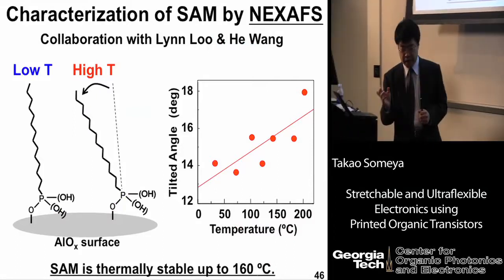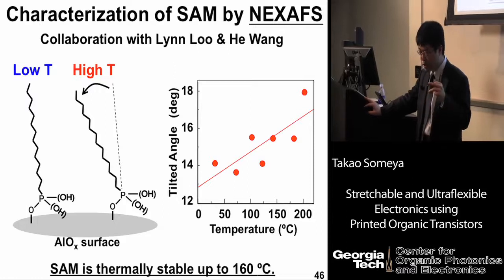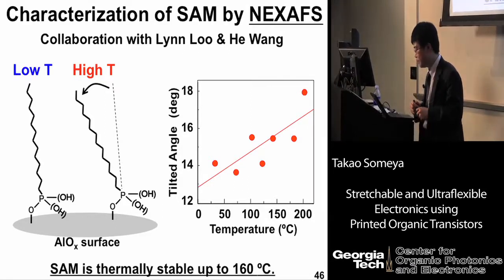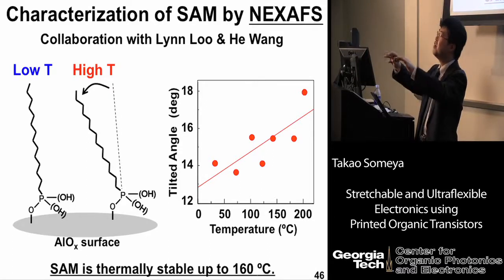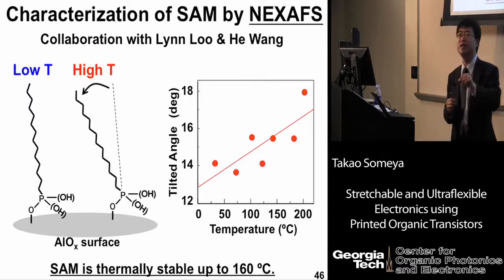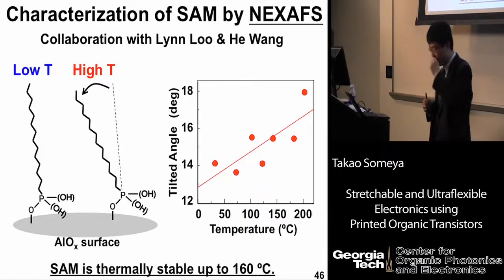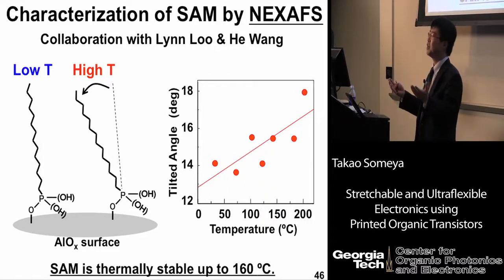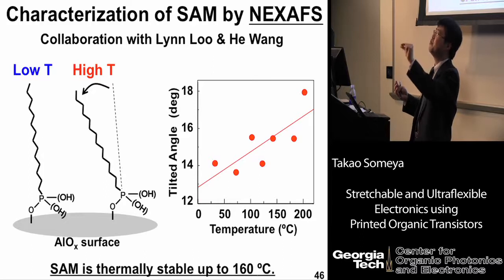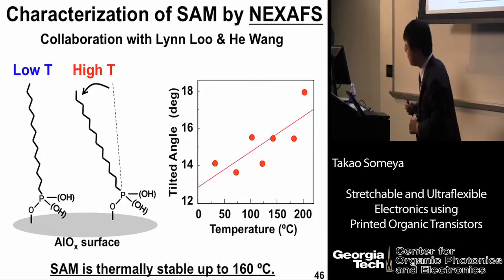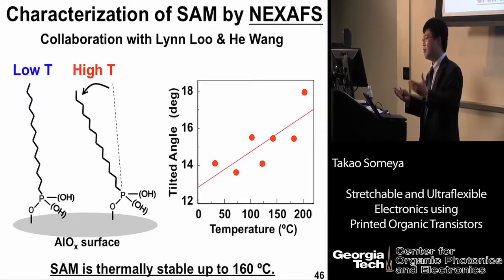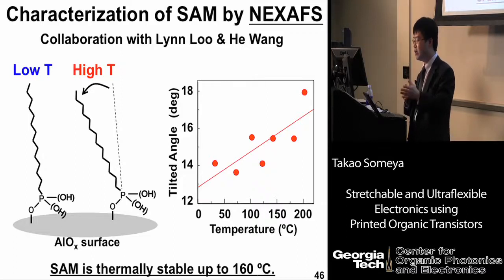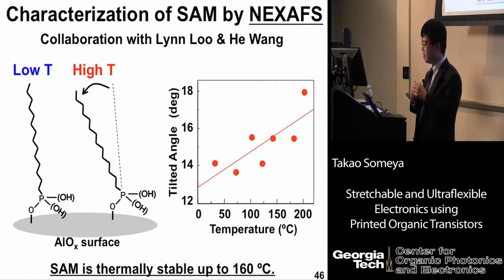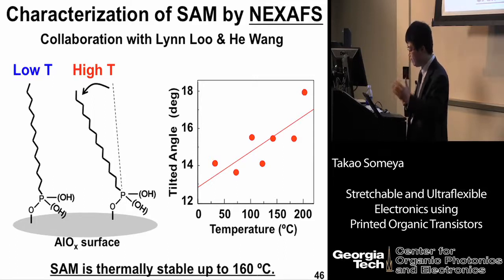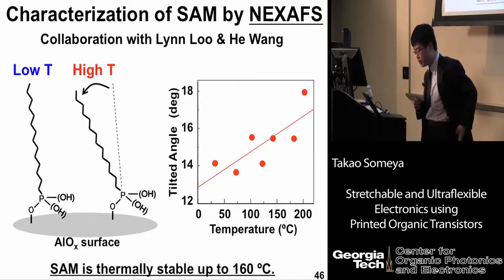However, here I also achieved an operation voltage of 2 V by using a self-assembled monolayer. But perhaps you may be concerned about the thermal stability of the self-assembled monolayer because it is only 2 nanometers in thickness. So the big question was whether such a thin film can be stable at temperatures exceeding 150 degrees Celsius. But by detailed structural analysis using NEXAFS, we found the self-assembled monolayer is extremely thermally stable even after we anneal at 160 degrees Celsius.